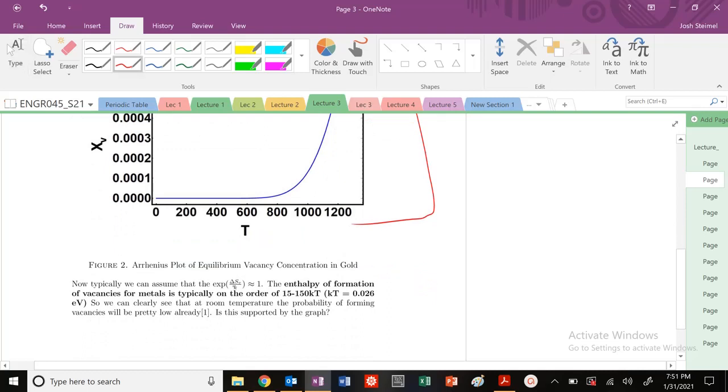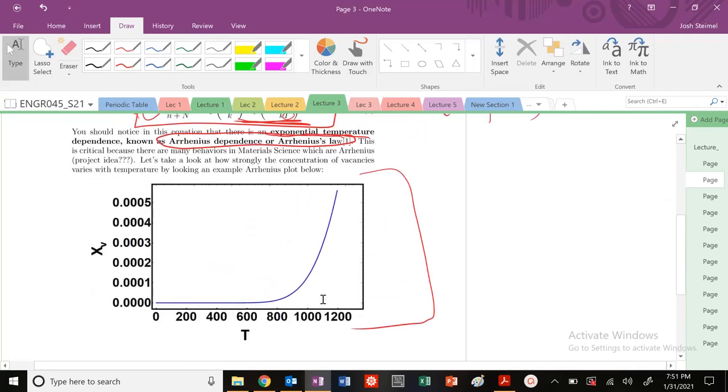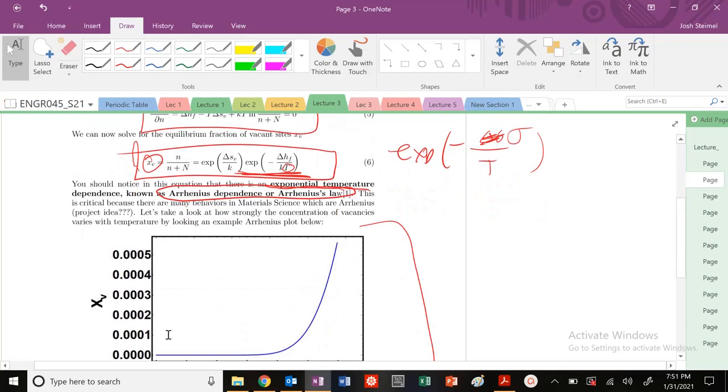For metals, you could usually assume this is true: the exponential of the delta S of vibration is going to be approximately equal to 1. And the enthalpy of formation for vacancies in metals is going to be 15 to 150, basically kTs. So we can do a little bit of work here to make this a more useful graph by taking a log. So let's look at this expression. If we know this is approximately 1, we know that we're going to get exponential of minus delta H F